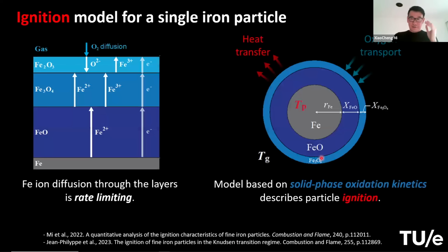And by knowing such an oxidation rate in solid phase, we can build a model to simulate the ignition process of an iron particle. We can build such a model by assuming this oxide layer is wrapping around a spherical particle. The growth rate depends on the parabolic rate law that we can get from the literature, using the experimental data to calibrate it. And then we can build a mass and heat balance model for this spherical particle system.